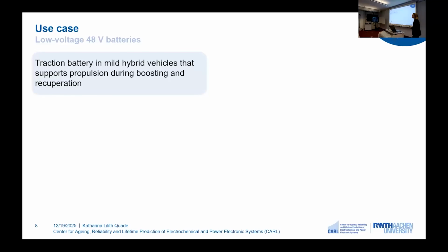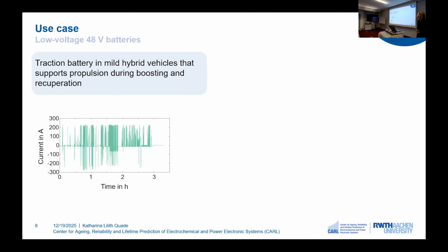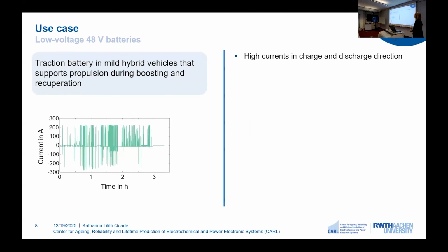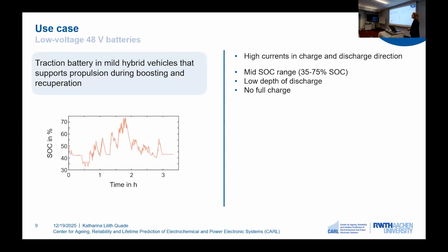This is a high-power automotive use case where we have 48-volt batteries that support the propulsion during boosting and recuperation. Here we can see a typical current profile. We have high currents in the charge and discharge direction. And when we now look at the relative charge, we can see that we are always moving in the mid-SOC range. We have low depths of discharge, and we do not have full charges. From the application, we also know that we have very demanding lifetime requirements of up to 10,000 equivalent full cycles, where one equivalent full cycle equals a full discharge plus a full charge of the battery.